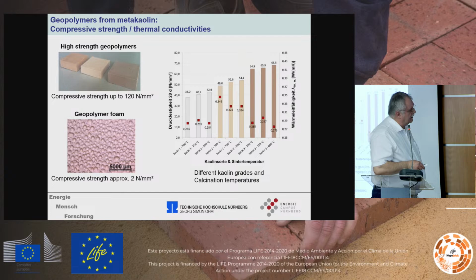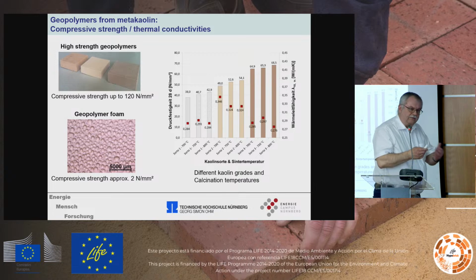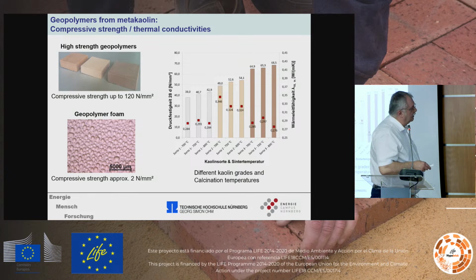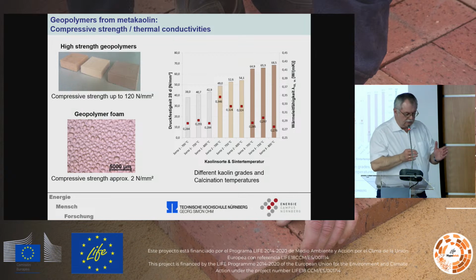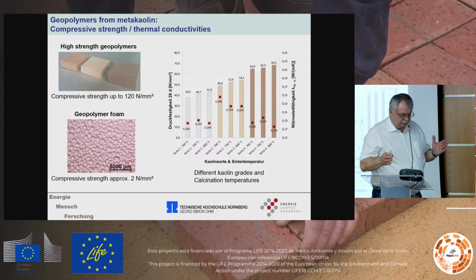And so you can have in the next step the 3D geopolymer network, and you see here an example for high-strength geopolymer. We can prepare this with a compressive strength up to 120 megapascal. Here it is Newton per square millimeter. It's megapascal. It's very high. And with the same reaction, with other chemicals, you can create a geopolymer foam. You see here the bubbles. And here the compressive strength is only 2 megapascal. You can make all things between that, foam or high strength.